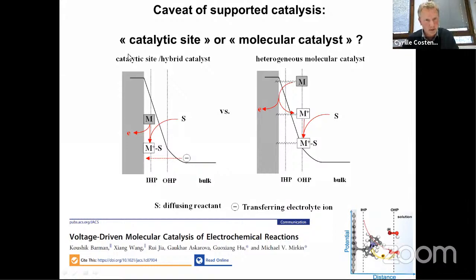Now, if you have a different situation where the catalyst is adsorbed in some way onto the electrode, so that the electronic levels of your molecule will mix with the electronic states of the conductive part of the electrode. So, for example, carbon powder, carbon nanotube, or graphene, or whatever. And then this means that as you polarize the electrode, the electronic states of your catalyst will move with the Fermi level of your conductor. And so now you don't have a molecular catalyst anymore.